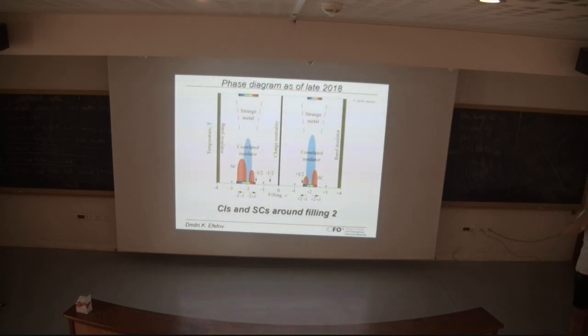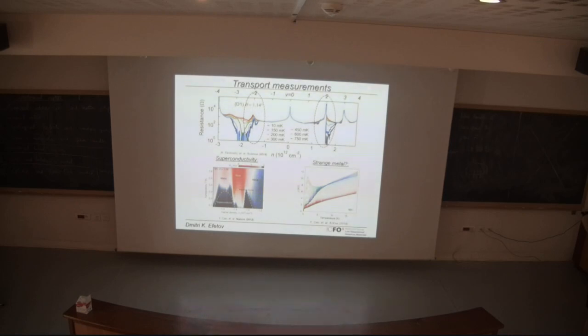On your previous slide, you said it's +2 and -2, but the range on the hole side is much broader. It's more like 3 and 2. So what causes this asymmetry? Okay, sorry, which asymmetry? On your top graph, you're saying you get a filling factor of 2 electrons or -2 holes, and you put your circle around it, indicating that that's where stuff starts to happen. But when I look at this, I would say that it's more around -3 than +2. Oh, so you see more happening here? Yeah. What causes this asymmetry? Mostly interactions. But I'll explain this data in more detail in the next slides.